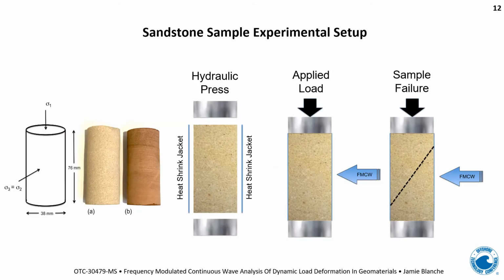And now to give you an overview of the experimental setup itself. What you see on the left-hand side are the sandstone cores as they were cut from the sandstone blocks. That is a 38 millimeter diameter and a 76 millimeter sample length, which is a standard dimension in geomechanical experimentation. You're also seeing sigma 1 being the axial load on the sample as applied, and sigma 3 equal to sigma 2, which is essentially saying that the radial confining pressure is equal and essentially zero.